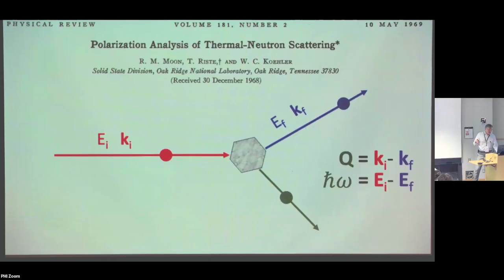Now, to really determine that spin structure is actually quite not so straightforward. And there are a couple of reasons for that. One is that it's a so-called Q equals 0 spin structure. And that means that the chemical unit cell equals the magnetic unit cell, which means that the magnetic Bragg peaks just fall on top of nuclear Bragg peaks. So they just change the intensity of some nuclear Bragg peaks a bit as a result of the magnetic structure. That actually becomes a bit of a challenge. But in addition, it's a non-collinear spin structure. And so there are many aspects of it that really cannot be determined by conventional unpolarized neutron diffraction.